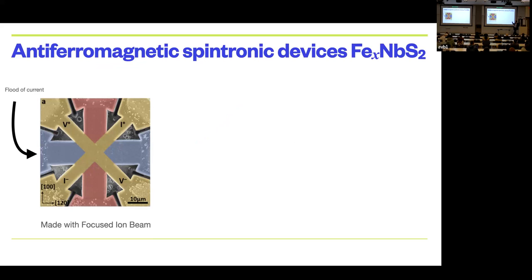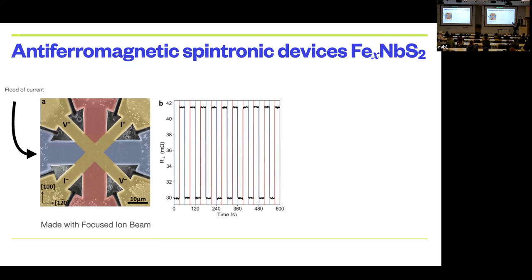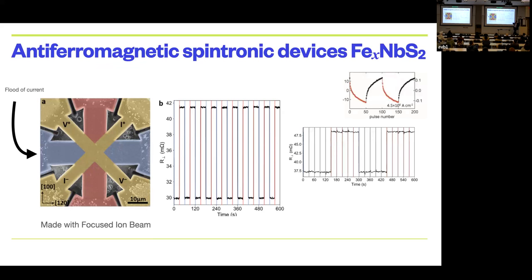We push current through the blue direction and the red direction. We see very stable, non-volatile switches, and they were like an order of magnitude larger than these other systems. And another interesting thing is that it didn't matter how many times you pulse this current along each of the directions, you always got the same resistance. Whereas for the previous systems, it seemed like you were getting a different resistance each time. Not only that, but the current that we needed to use to get this up and down behavior was like 2 orders of magnitude lower than these other systems, and it was like an order of magnitude faster.